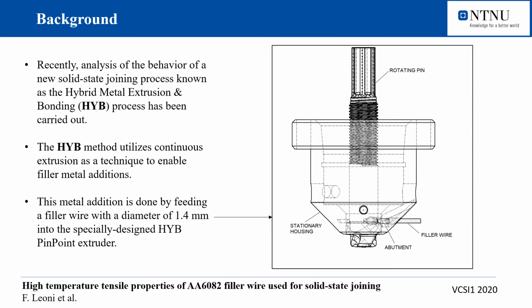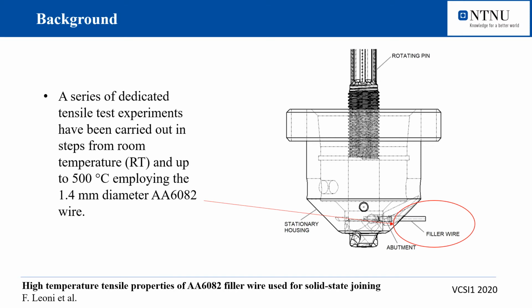In a previous work by the authors, the software package Deform 3D has been successfully employed in modeling the material flow pattern inside the pinpoint extruder, using the default flow stress data provided by the software material library. But now, to upgrade the material properties used as input to the simulations, a series of dedicated tensile test experiments have been carried out in steps from room temperature up to 500 degrees Celsius, employing the 1.4 mm diameter aluminum alloy 6082 wire. This covers the entire temperature range typical of the extrusion process.